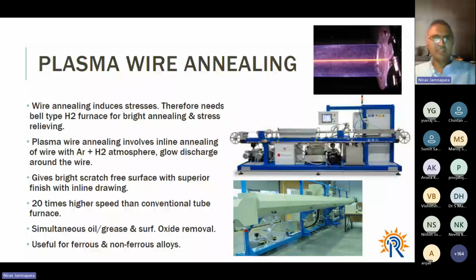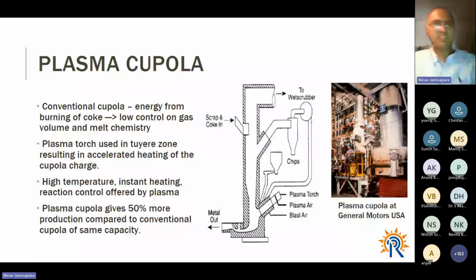The final technology that I'm going to talk about is the plasma cupola. Conventional cupolas are basically driven by burning of coke, which is high grade metallurgical coke, but it has low control on gas volume and the melt chemistry. The plasma torch, when used in the tuyere zone, the bottommost zone just above the tapping point, results in accelerated heating of the cupola charge. It also gives very good control of the gas chemistry. Therefore, high temperature instant heating and reaction control are offered by the plasma torch in the cupola. And this plasma cupola gives 50% more production compared to the conventional cupola of the same capacity.